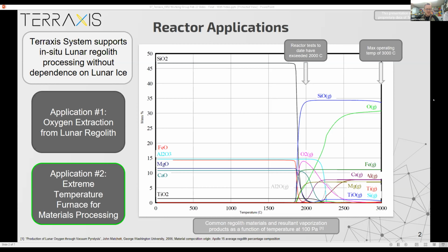You start with these different metal oxides, silicon dioxide being the most prevalent in lunar regolith. Then once you get just under 2000 C at this particular pressure, these different metal oxides disassociate into, well, different oxygen compounds, but also different elemental metallic compounds like iron, magnesium, aluminum, etc. So our focus was originally to work on this as an oxygen generation tool. However, all these other products get generated as a matter of course, because in order to get the oxygen out, we're already surpassing the temperatures where we get these other compounds out as well.